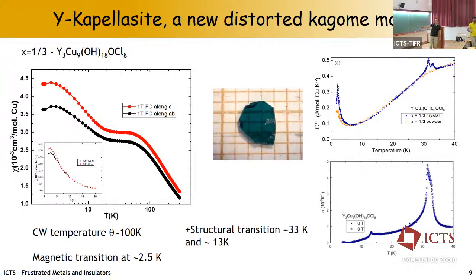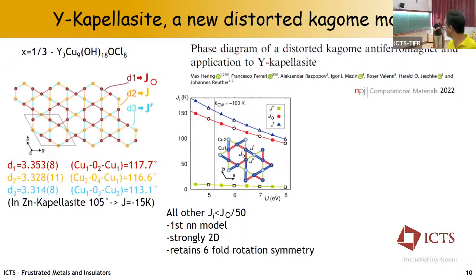Well, imagine there is a small peak there, resolved there at 12 K. I'll tell you more about it. So what can we imagine for the magnetic model? Here we are helped a lot by the theoretical study of colleagues, including in particular the first-principles calculation from Harald. From this calculation, it turned out that the important interactions are only the nearest neighbor ones. The other ones are much, much smaller, like a percent of the main one. So there is no interlayer coupling and there is no further intralayer coupling either.